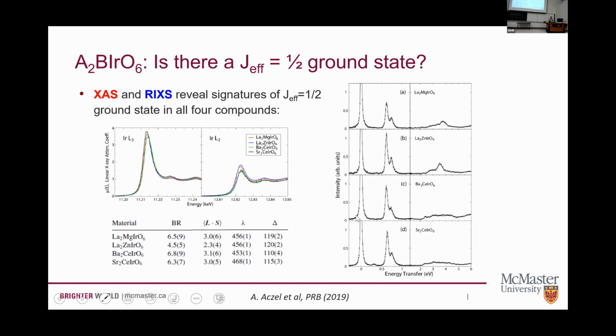And if you go from these double perovskites, some of these have structural transitions as a function of temperature. You can look at the high temperature cubic state and the low temperature monoclinic state, and there's very little difference here. So we know from looking at other iridates, from looking at pyrochlores, that there are longer range crystal field effects that can complicate things, that it's not all just the immediate iridium oxygen shell, but this one is still a surprise as to why there's not more difference between them.